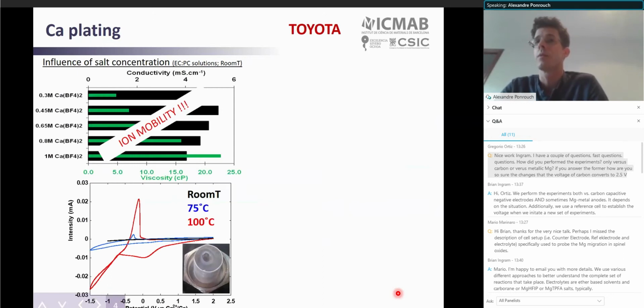A few years ago, we tried to reinvestigate a bit this research field, and we were able to assess the feasibility for calcium metal deposition, and identified one crucial parameter, which is the cation mobility within the electrolyte. By increasing a bit the temperature, we were able to plate and strip metallic calcium.